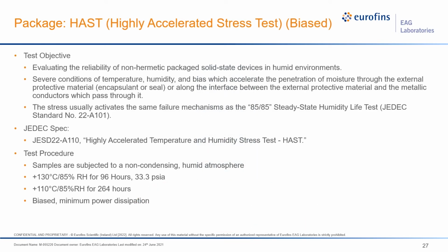Highly accelerated stress test, known as HAST. This test is performed to test a package for corrosion resistance, and that the package insulation does not allow moisture inside the package. The failure mechanisms seen from the biased HAST are corrosion, oxidation, electromigration, and delamination.